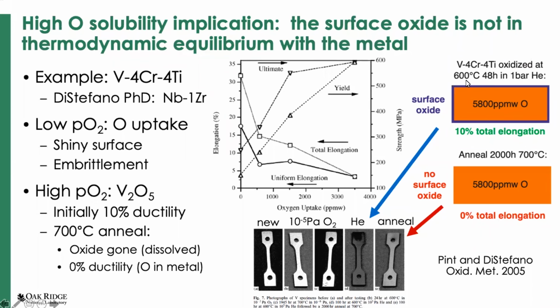But here's the problem with high oxygen solubility. That oxide is not thermodynamically stable. So again, we just repeated what Jim had done about 50 years earlier, or maybe 40, that 2,000 hour anneal at 700 degrees C, the specimen comes out and there's no longer any oxide on the surface. It didn't fall off, it dissolved. Because again, that oxide in contact with that metal is not stable.